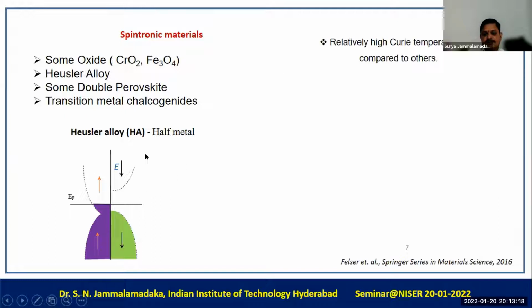As far as their Curie temperatures are concerned, it is also very important to look at whether the Curie temperature of that particular material is very high or not, so that one would be able to use these materials for device applications. It must be above room temperature. The Heusler alloy materials are the ones which have Curie temperatures above room temperature. So these Heusler alloy materials have relatively high Curie temperatures.